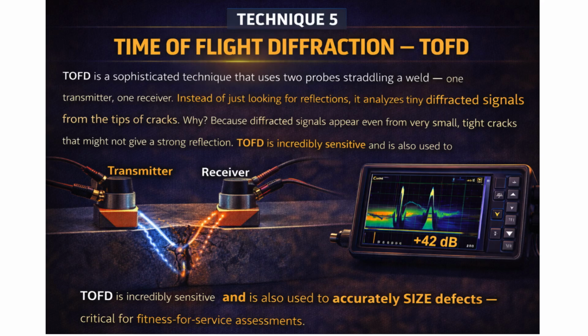Time of flight diffraction, TOFD. TOFD is a sophisticated technique that uses 2 probes straddling a weld, one transmitter, one receiver. Instead of just looking for reflections, it analyzes tiny diffracted signals from the tips of cracks. Why? Because diffracted signals appear even from very small, tight cracks that might not give a strong reflection. TOFD is incredibly sensitive and is also used to accurately size defects, critical for fitness for service assessments.